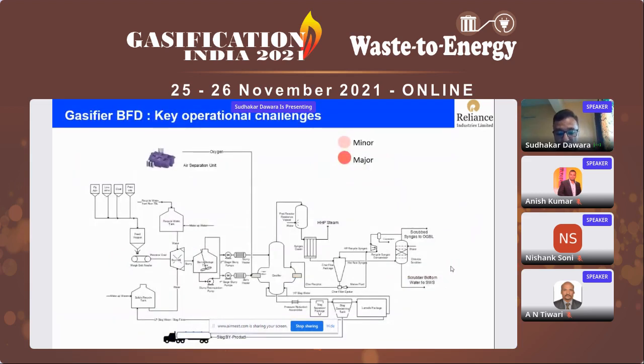Here, on this journey, as Mr. Tiwari mentioned, it's not easy, and as in every gasification plant, we had a lot of challenges. Starting from the first point, we had challenges with feed flux management. We had challenges in controlling the slurry quality. We had a lot of issues in the slurry storage, because when we say slurry, it's a misnomer. It's not actually a slurry. It's a 60 to 65% concentration, and it's almost like a paste. The viscosity is in the range of 100 to 1000 cP. So basically, it's a paste, and we have to push it.